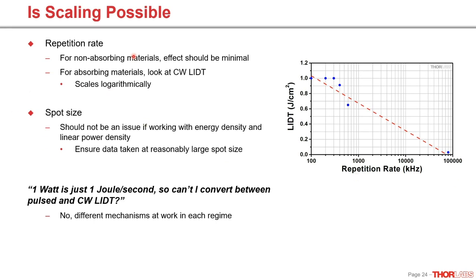As far as spot size, this shouldn't be an issue if you're working with energy density and linear power density, so that's joules per centimeter squared and watts per centimeter, as long as your data was taken at a reasonable spot size, which is typically at least 100 to 200 microns. If you have data taken, say, at 10 or 15 microns, you may wind up vastly overestimating your damage threshold as you scale. But with larger spot sizes, that shouldn't be an issue.